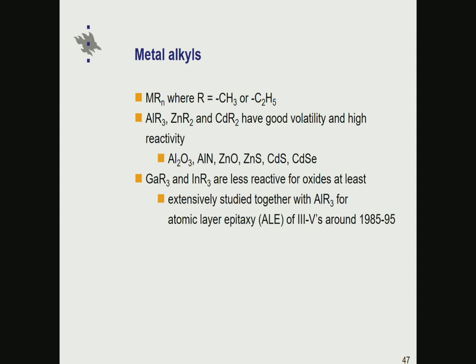Metal alkyls, in those cases where they are available, are really useful. In the ALD field, it's mostly aluminum, zinc, and cadmium where these have been used. Out of these, aluminum and zinc of course dominate over cadmium, which has these concerns related to its toxicity. These are the main materials deposited from these.